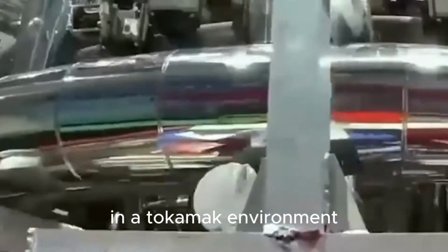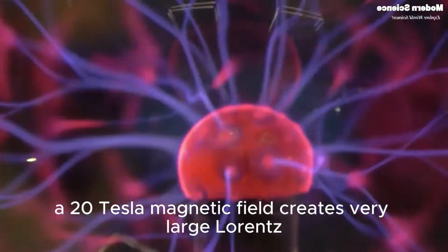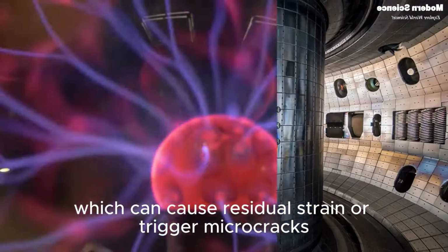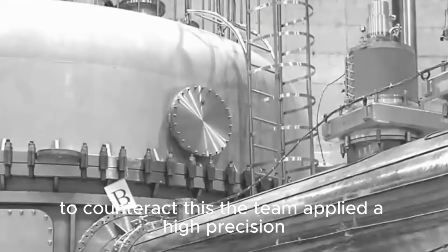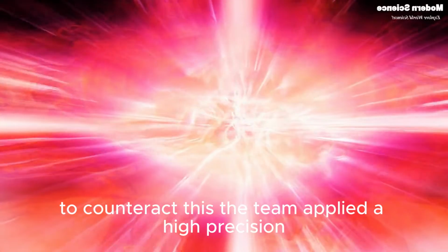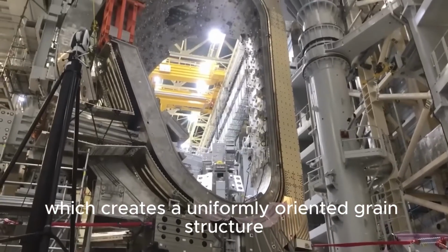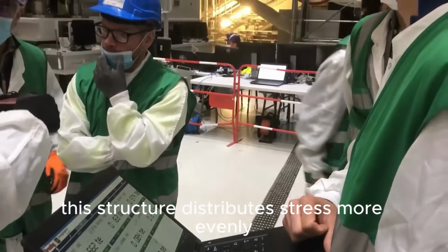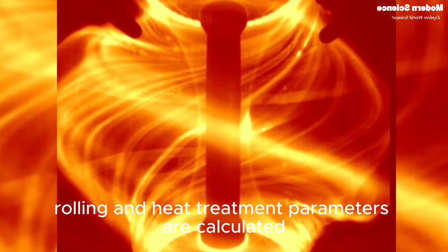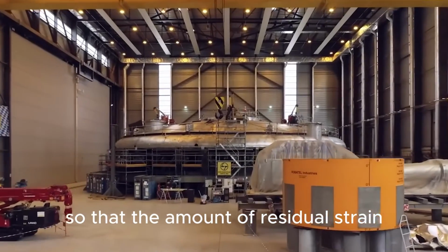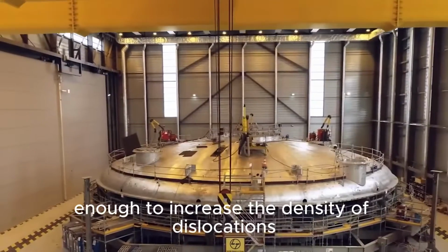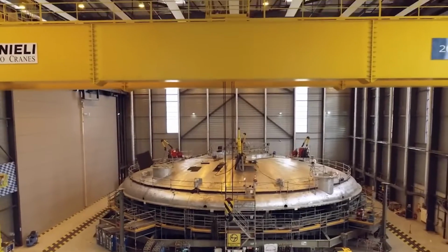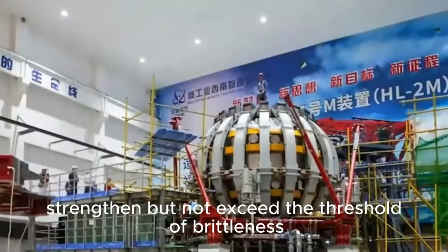Another issue that scientists had to address was the effect of strong superconducting magnetic fields on the material. In a tokamak environment, a 20 Tesla magnetic field creates very large Lorentz stresses, which can cause residual strain or trigger microcracks. To counteract this, the team applied a high-precision cold deformation rolling technique, which creates a uniformly oriented grain structure. This structure distributes stress more evenly and limits stress concentrations, the main cause of failure under harsh conditions. In addition, rolling and heat treatment parameters are calculated so that the amount of residual strain is at an optimal level, enough to increase the density of dislocations, strengthen, but not exceed the threshold of brittleness.